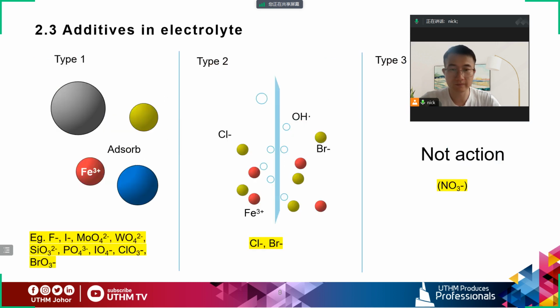The third factor is additives in the electrolyte. Different additives in the electrolyte have varied mechanisms of influence, closely related to the electronegativity of the additive. One type of electrolyte ion is adsorbed around ferric, reducing the catalytic decomposition of the ferrate by ferric. Other types of electrolyte ions can trigger the generation of free radicals, promoting higher ferrate production.